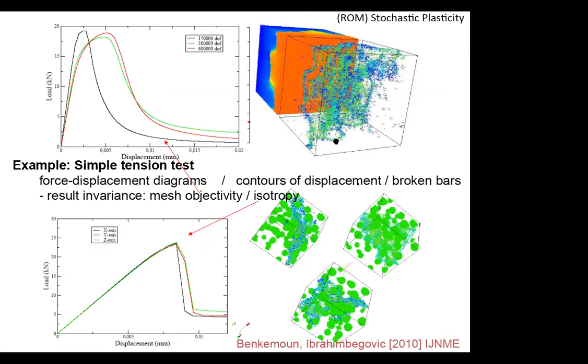What this model can do is really remarkable. You cannot do this in testing. You do a simple tension test, you show that 150,000, 300,000, 600,000, you start converging. You get really a failure in tension. You cannot even do this test because if you put a specimen in a testing machine in simple traction, you're going to squish it before you break it in tension.